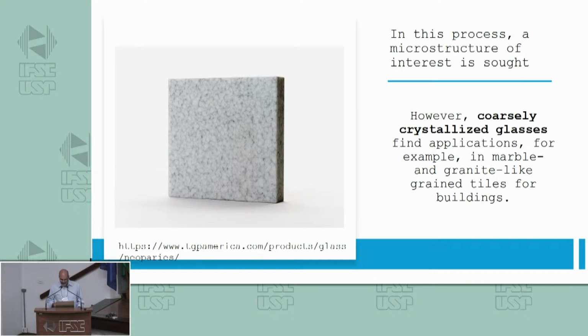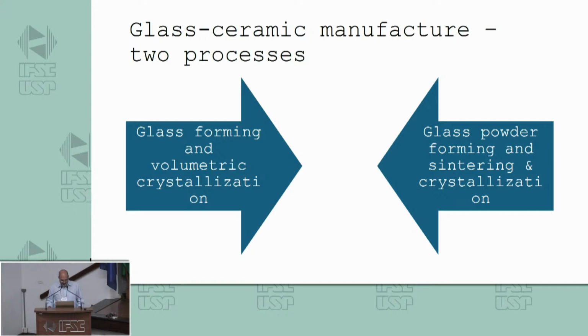So there are a lot of possibilities using this process. In general, there are two main routes that we could follow to obtain a glass ceramic. The glass can be crystallized in the volume by a proper design of composition and addition of nucleation agents. But we can also use a glass powder form, using the traditional methods found in the ceramic industry, and then treat it for sintering and crystallization, which Ralph talked about a lot in the last talk.